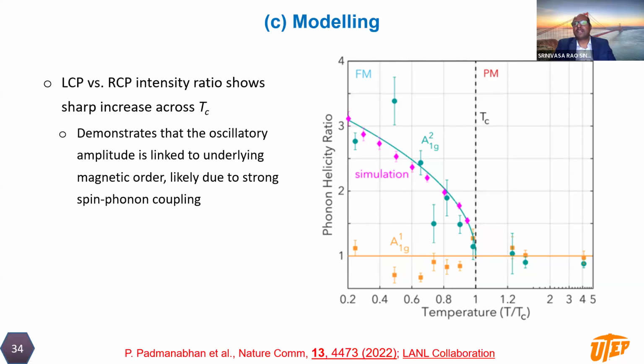That shows that there is strong interaction between the electron spins of this compound and phonon vibrations. So that tells us that we are looking at strong spin-phonon coupling through the magnetostriction effect.